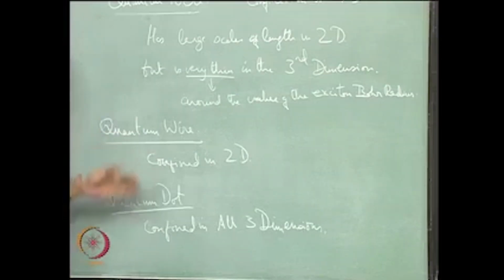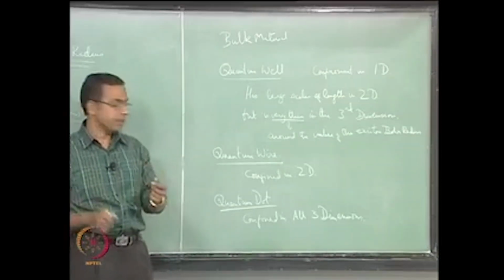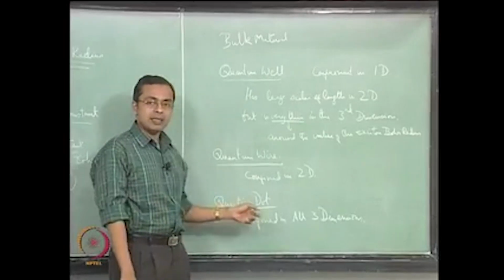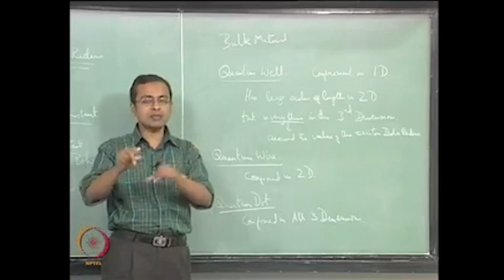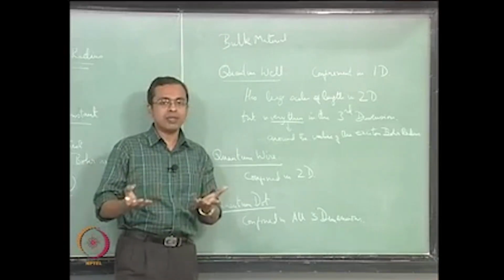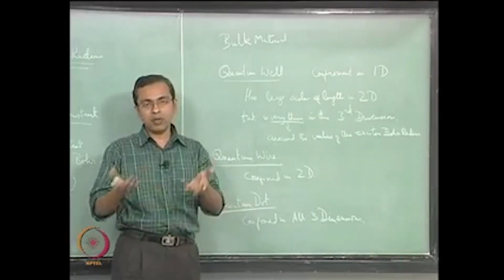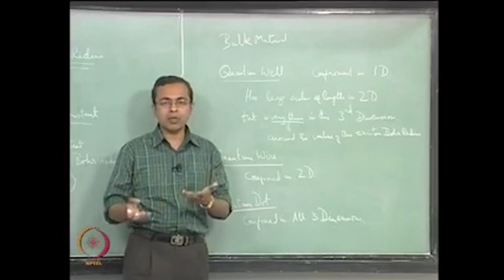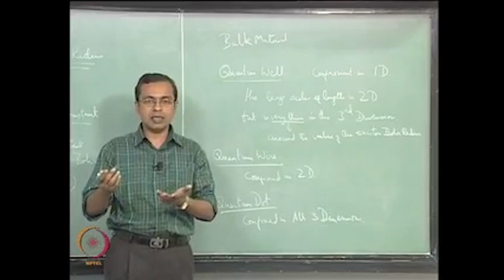There are of course a lot of very interesting scientific challenges in doing this, because when you make such tiny particles they are usually very highly reactive, so they will not stay as tiny particles for too long. If you make such tiny particles they will simply react with each other and agglomerate. So one of the scientific challenges is to freeze them such that they do not get in touch with each other and grow. One of the ways this is accomplished is to grow them inside a polymer matrix. Many polymers will typically have pores inside them which are in the nanoscale.